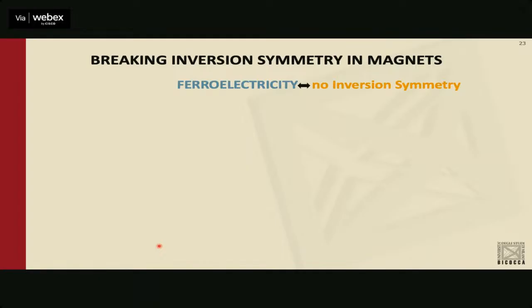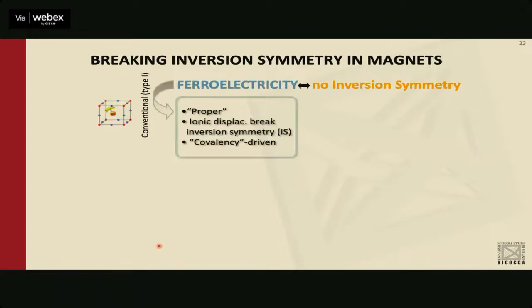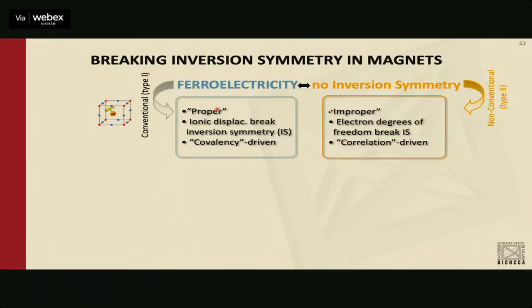And so this is basically a slide that I showed for the ERC interview. So that is my activity for many years. So you have ferroelectricity breaking inversion symmetry. And in a standard ferroelectric, it's basically the ions that break inversion symmetry. And you have a so-called proper ferroelectricity. Proper means that ferroelectric polarization is the only order parameter of the transition. But you can choose an alternative way. You can choose the electronic degrees of freedom to break inversion symmetry. So in this case, ferroelectricity is improper. So the primary phase transition is driven by electronic degrees of freedom. It's just that as a byproduct, you break inversion symmetry and polarization will pop up.